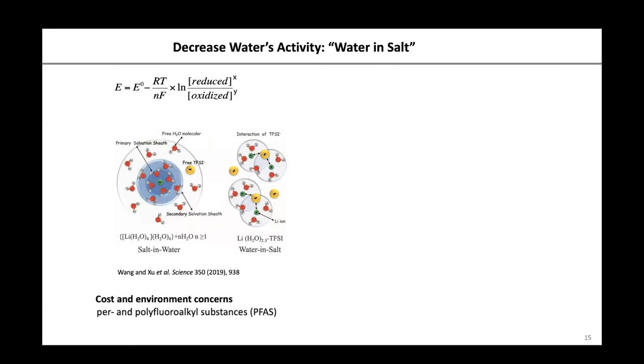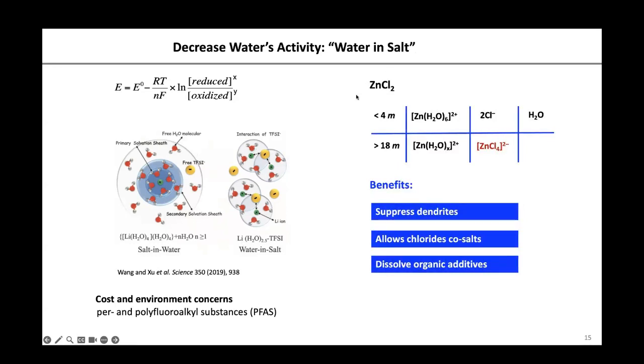Well, there are some issues with TFSI and other fluorinated molecules due to the cost and environmental concerns. So in my lab, since 2017, we have focused on zinc chloride. Zinc chloride is cost effective and it's not toxic. And most interestingly, if you use different concentrations, the speciation of ions in this electrolyte will vary dramatically. If you have a low concentration of zinc chloride, the cation, of course, is hydrated zinc 2 plus. The anions are chloride. But if you make this electrolyte highly concentrated, the anion now is tetrachlorozincate, right? That's very interesting.